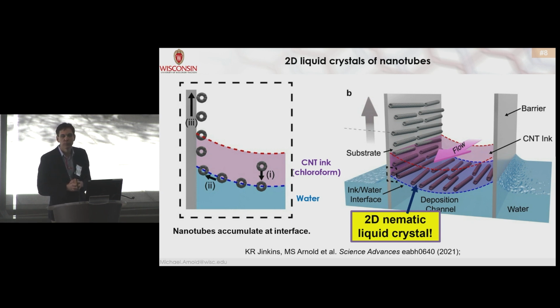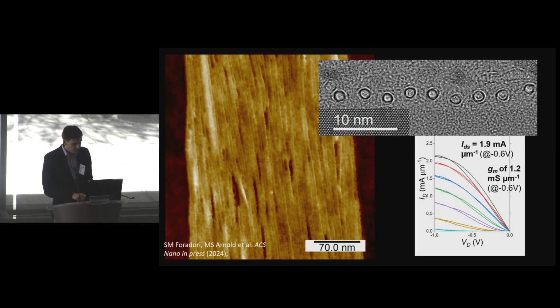One really cool approach we're exploring right now is to form liquid crystals out of nanotubes. So the nanotubes are the liquid crystal element themselves. If you take those nanotubes floating in solution, wrapped by the polymer, in an organic solvent, that's the purple color there, and layer that on top of water, the nanotubes go to the interface between the two solvents and form a two-dimensional liquid crystal. Whenever you have a high density of rod-like objects, they align themselves. That's what a liquid crystal is. So we could get the nanotubes to align themselves, then pull a substrate out to pick them up onto that substrate, and we can get very dense arrays of aligned nanotubes.